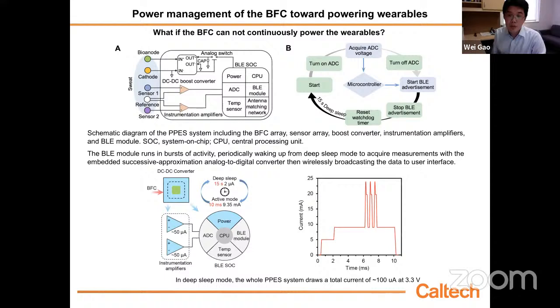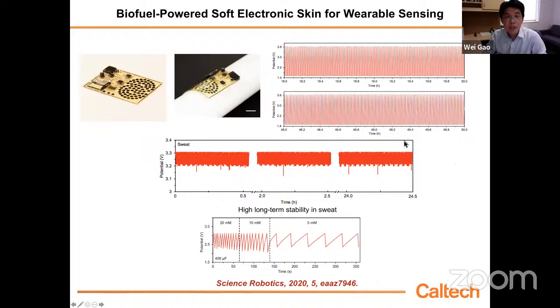So we can put the entire system to sleep. When we get enough power, we wake our system and do a quick measurement with wireless communication. So basically every several seconds, we can get a measurement using this system. You see deep sleep for a few seconds and wake up for a very short period to do the measurement. So we integrated the entire system into a soft electronic skin. It's flexible, as you can see here.